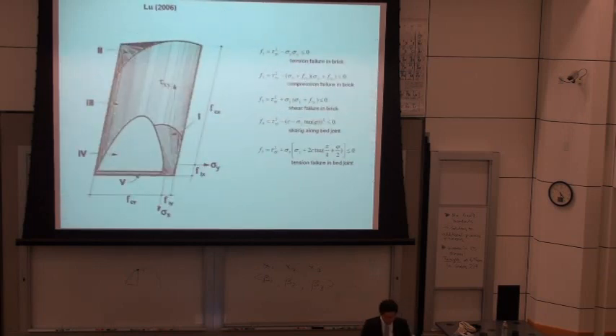I've made a model in 2006, a three-dimensional model, which is based on the model of Ganz in Switzerland, and have extended the three-dimensional failure mechanism with some tensile failures. So with five failure criteria also: tension failure in block or brick, compressive failure in brick, shear failure in brick, sliding along the bed joints.